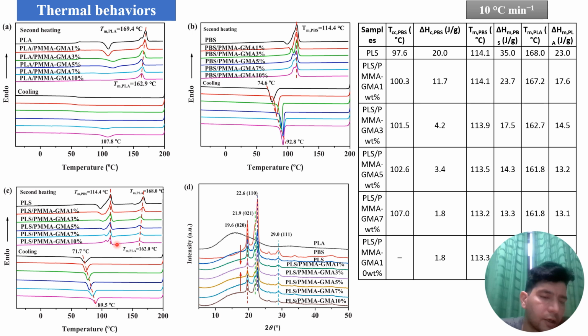Now come to the blend, which is the most important one. In the blend system, this is for the pair PBS and PLA. So this is the blend, and it shows two peaks. This peak is because of PBS at 114.4 degrees centigrade, and this one is because of PLA. Here it is discussed that the Tm because of PBS is 114. By adding the compatibilizer, it decreases slightly, which means they show a little bit of miscibility. Same as in the PBS, the second melting peak is also observed, which means they improve the crystallization.